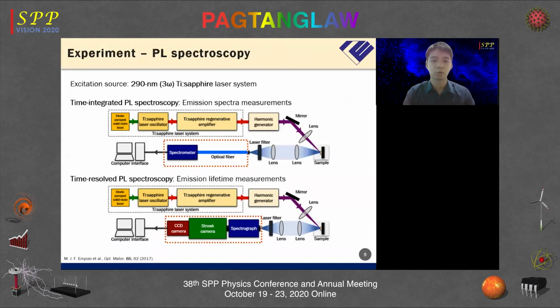We then performed photoluminescence spectroscopy on the hydrothermal grown zinc oxide nanostructures at ILE. The samples were excited by a 290 nanometer titanium sapphire laser system, and the sample emissions were collected through reflection geometry using a handheld spectrometer to measure their emission spectra, or a spectrograph coupled to a streak camera to measure their emission lifetimes.